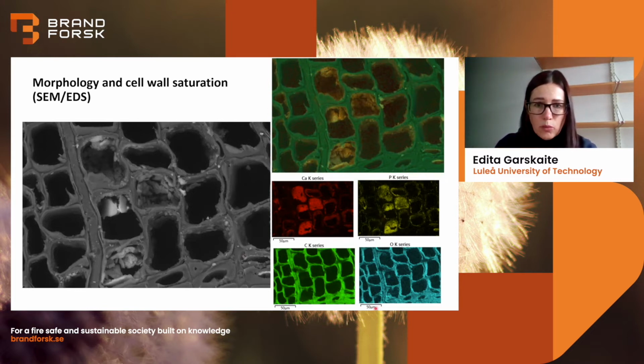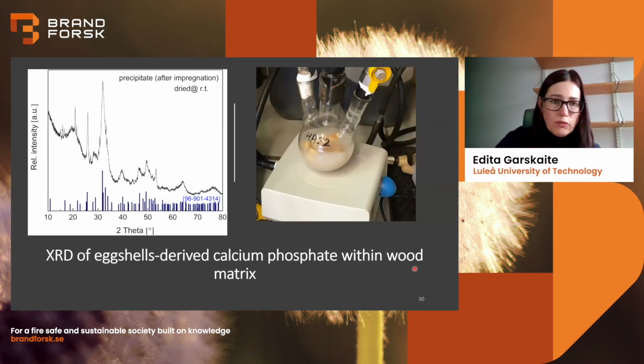So here are carbon and oxygen, how it shows when you assign different elements. In the wall, we have mainly carbon, which is coming from the wood, of course. And then on the top here, we have a mixture of these elements. So when you mix red and yellow, you get orange, and you see that way it is our calcium phosphate. Now let's see at structure what we got.